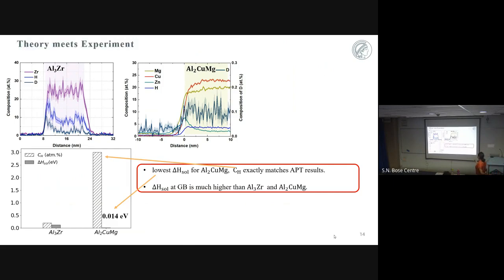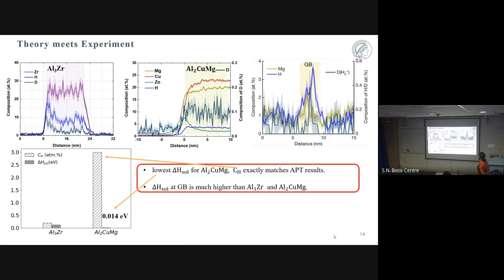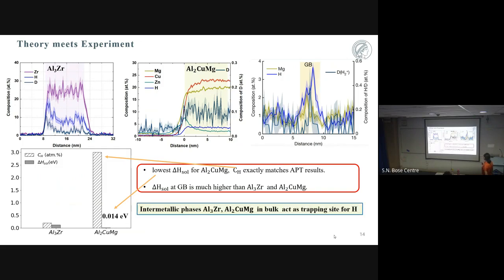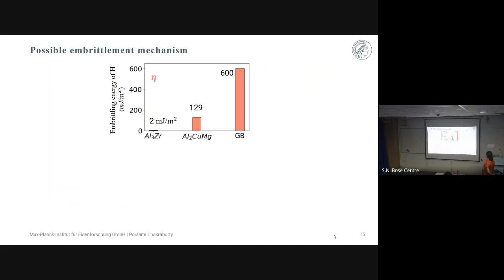Now I will present how our theory is complying with experiment with the grain boundary structure. As you can see, among all of these intermetallic phases and the distorted alloy system, the grain boundary has the least amount of hydrogen trapped in it. Therefore, from here we conclude that the intermetallic phases in bulk act as trapping sites for hydrogen. And we will discuss the possible embrittlement mechanism.